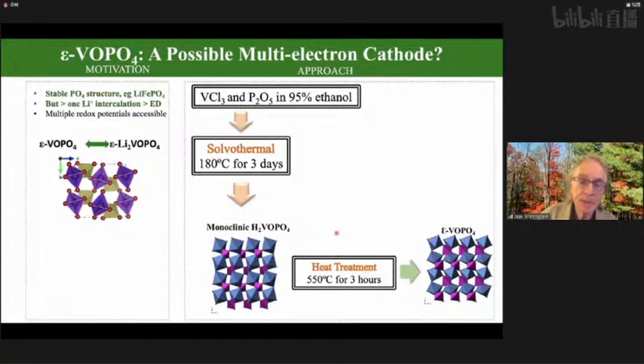So what is this material? It's a tunnel structure. In this case, the tunnels are in all 3 directions. And what we're interested in doing is putting 2 lithiums into this lattice. And the way we made this was using a soft chemistry approach. So we dissolve all our reactants into a solution, in this case 95% ethanol. You need about 5% water to stop over reduction of the vanadium. Then you just heat it up for 1 to 3 days at about 180 degrees centigrade.